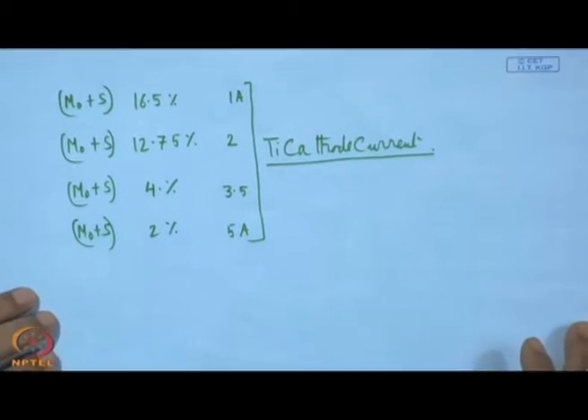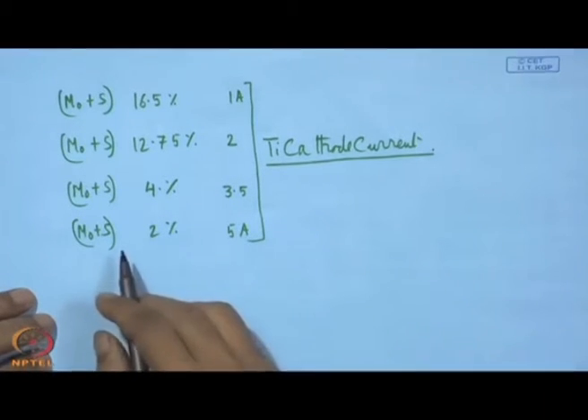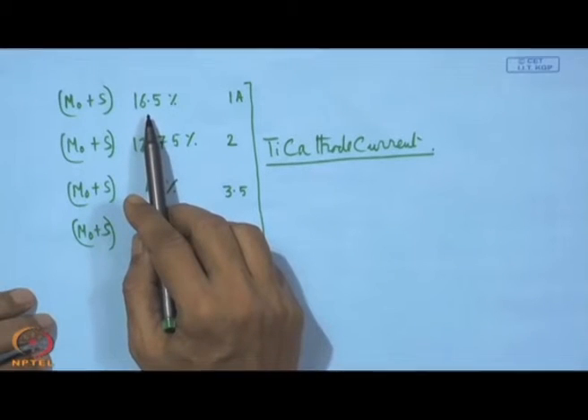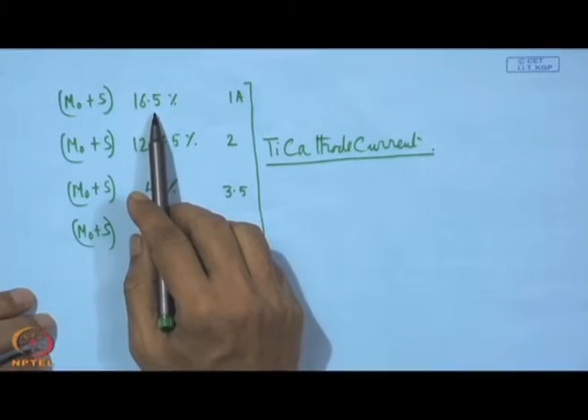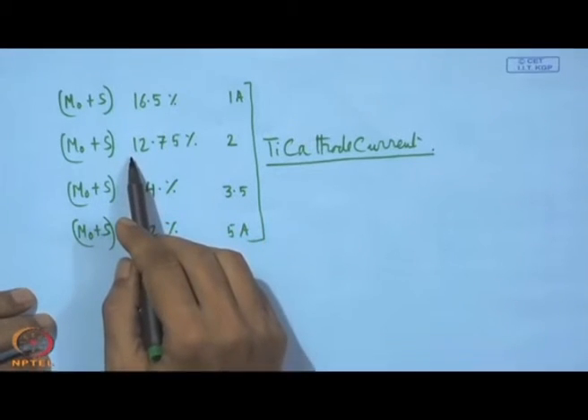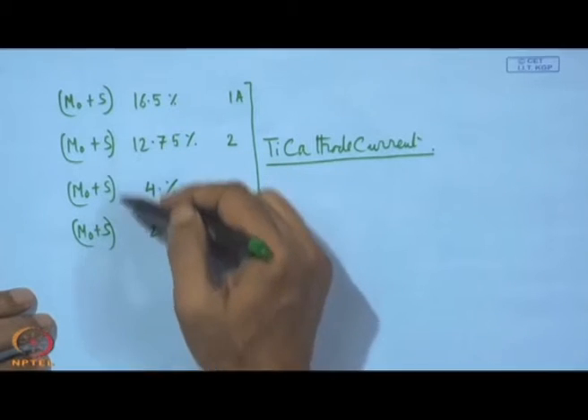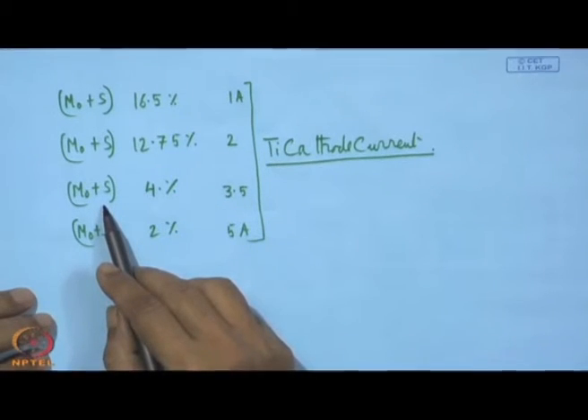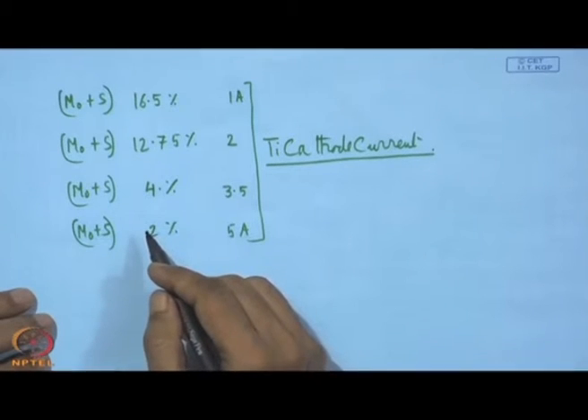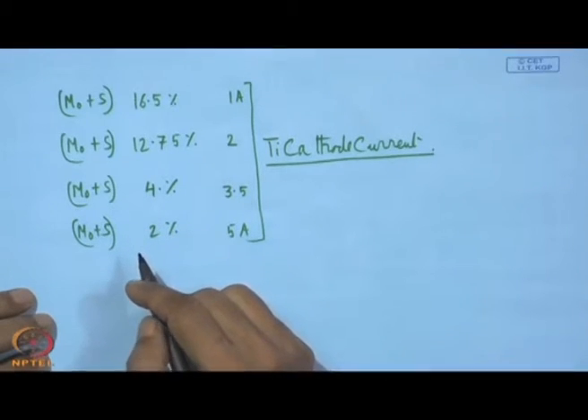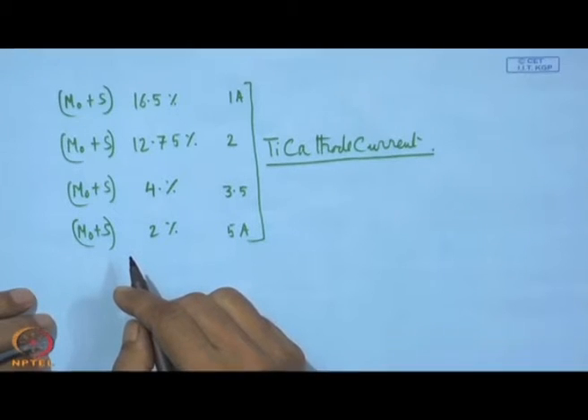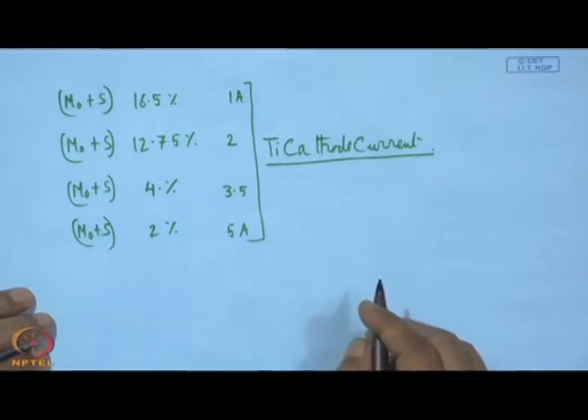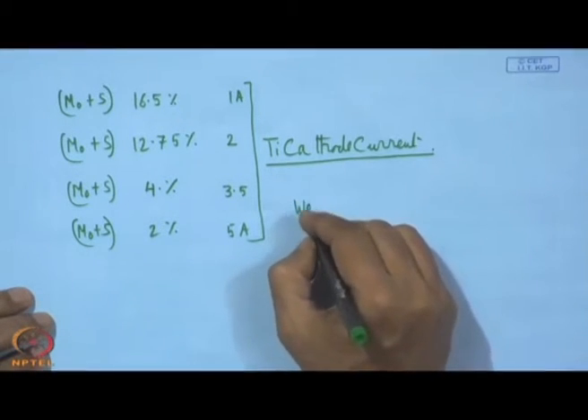So, with this what we see is that the friction coefficient for this one is going to be the lowest, followed by this composition. So, the lower the value of MoS, the higher will be the coefficient of friction. However, what is very important to know here is that we also have another term, what we call the wear coefficient.